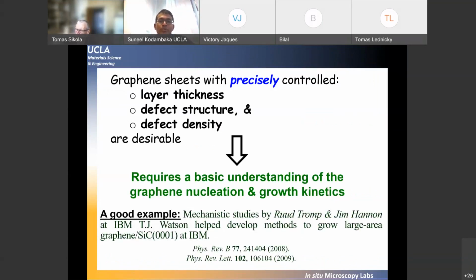And other studies have also shown that the properties of 2D layered materials depend on the layer thickness and the layer orientation. And so one needs to understand how these layers grow, how they're oriented, and how we can control this orientation. And this, I believe, can only be achieved by fundamental studies focused on how the layers nucleate and grow. One ideal example that I can think of is the studies that were done by Ruud Tromp and Jim Hannon at IBM TJ Watson, who helped develop methods to obtain single domain graphene across a 3-inch wafer at that time on silicon carbide surfaces. They carried out LEEM studies to identify how the graphene grows on silicon carbide, and using that information, they developed methods to perfect the growth of graphene layers on silicon carbide.